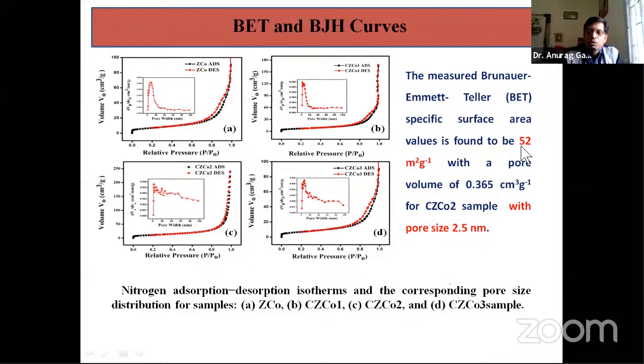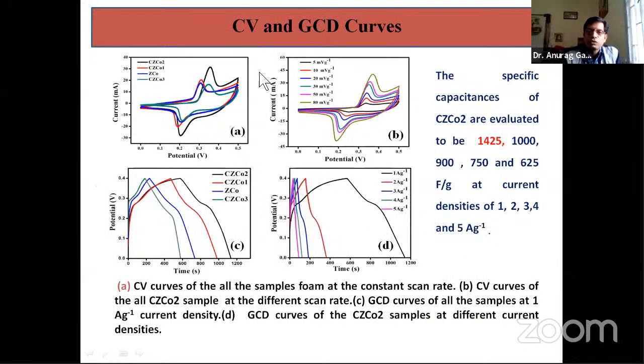We have seen that the surface area is 52 meters square per gram, and the pore size is 2.5 nanometers. So again, it is in the mesoporous range. Now this is the CV curve. You see that again the oxidation and reduction peaks are there, indicating the pseudocapacitive nature of the material. It is pseudocapacitive and non-linear as well.